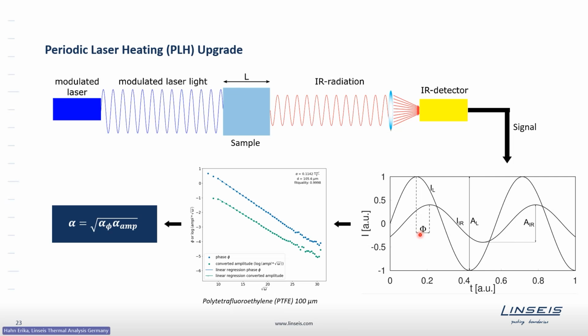This we collect and evaluate using a lock-in amplifier. So we have in the end a look onto the phase shift and the change of the amplitude from the induced signal to the reflected signal of the sample. We evaluate it to have a linear relation, as linear relations are easy to evaluate. And in the end, we also get the thermal diffusivity out of the measurement. So this PLH method is an extension for thin films, and both modes can be used in the same setup.